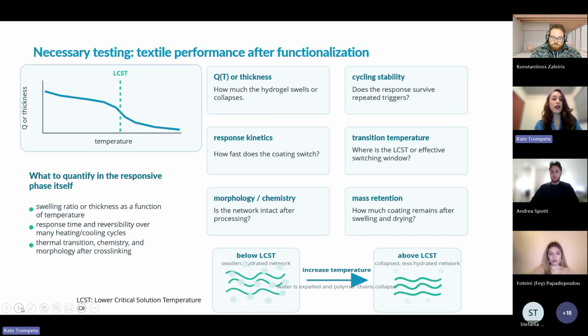It stands for the lower critical solution temperature. Below LCST, the network is hydrated and swollen. Above it, we have a less hydrated polymeric network that can also be collapsed. So it means that the water is expelled and the polymer chains collapse. These are done through the increase of temperature.